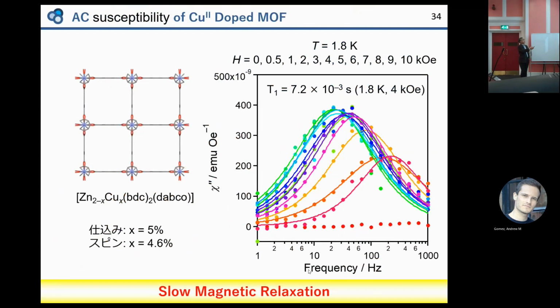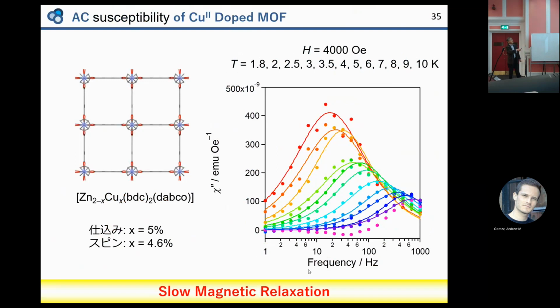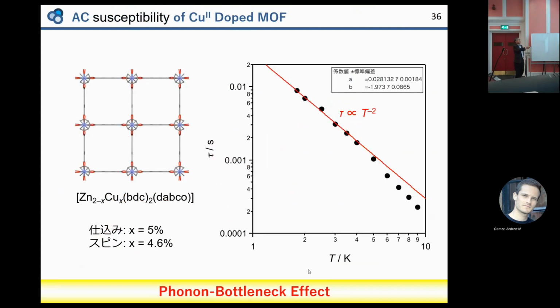So this magnetic dependency, very beautiful frequency dependency, slow magnetic relaxation. One copper ion shows a slow magnetic relaxation, and temperature dependency of the slow magnetic relaxation is observed. This is due to the phonon bottleneck effect. So from the fitting, this slow magnetic relaxation is due to the phonon bottleneck effect.